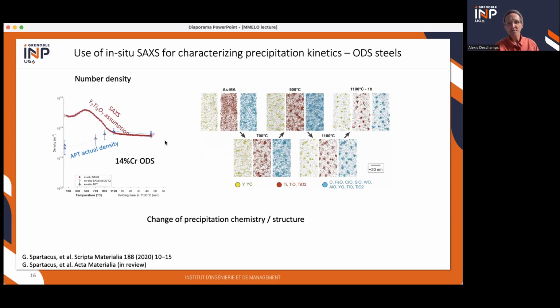Very interestingly, at the end of the process, you have a perfect agreement between the two. So the SAXS number densities are exactly the same as atom probe, which is quite reassuring. But initially, there is a one order of magnitude difference between the two. And we're still not exactly sure where this comes from, but basically it's a sign that the assumption of small angle scattering was wrong, and that these precipitates have not yet reached the full equilibrium structure yet.